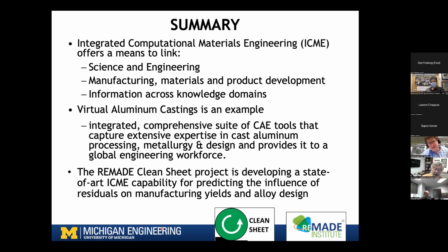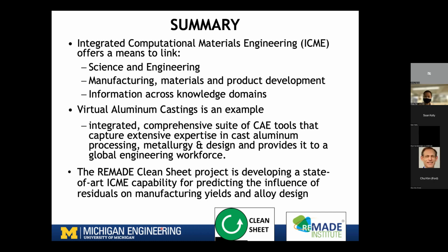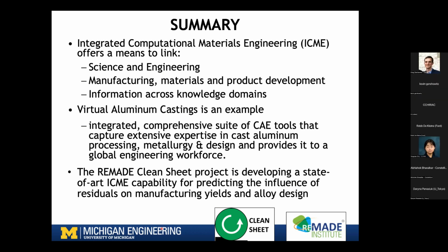Well, not really, because oftentimes those critical locations are difficult to get material properties from. Take a valve bridge in a cylinder head, very critical area, but it's a very tiny area. And so it's not really possible to take average properties from that. So oftentimes that was done by build it and bust it testing. And so basically using this approach, we replaced a lot of average properties with large safety factors and lots of testing, substantially reducing the testing requirements and improving the designs at the same time.